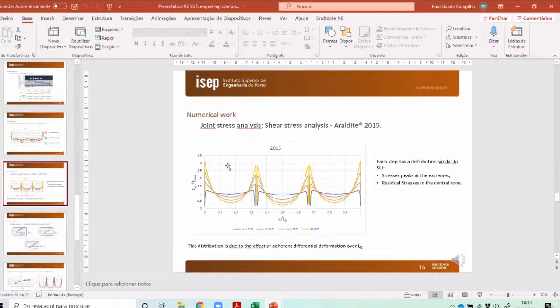Would it work if you were applying the ductile adhesives on the two sides where you're having the peak values, and in the middle you can use the stronger adhesive that is brittle? Yes, it is a technique that is used in some cases in single lap joints. In step lap joints, we can also, for example, put a more ductile adhesive in the edge steps and a more brittle adhesive in the middle step. Yes, it would be a possibility to improve the behavior of the adhesive.